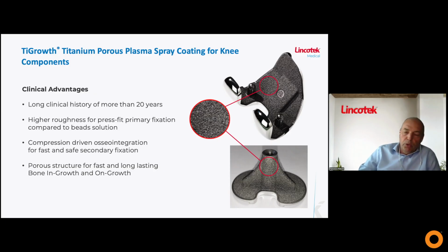So in conclusion, for what relates to the coating for knee components, the clinical advantage of highly porous and thick coatings like TiGrowth is that you can rely on a long-term application with a consolidated 20 years of applications. The higher roughness that this type of surface provides is suitable for primary fixation. The compression-driven osseointegration is suitable for secondary fixation, and the porous structure is suitable, as we have seen, for fast and long-lasting bone growth and bone ongrowth.